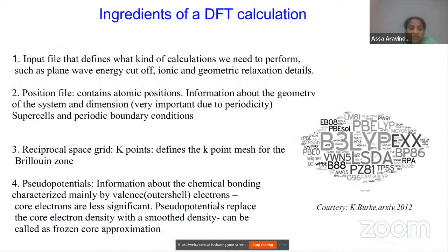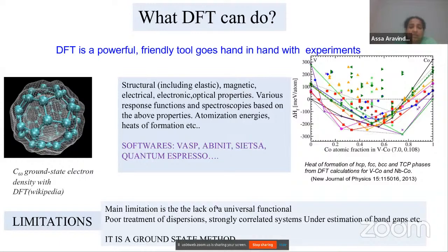But even though we can calculate all these things, the main limitation, as I was telling, is the lack of a universal exchange correlation functional. And for certain systems, when you use DFT, you should be very careful. For example, Van der Waals monolayers, the treatment of dispersions, you should be very careful. And also there is underestimation of band gaps for strongly correlated systems. So you need to know what system you are using and what material is best suited for that. When you compare with experiments, it's good to have a qualitative comparison rather than a quantitative comparison. For example, we calculate the band gap of some insulator as 3 eV in experiment. When you do DFT, maybe you can only get like 2.5, that much accuracy is maybe only possible to achieve in some cases. So you should be aware of that. But nevertheless, we can see the trends, how the trends are varying, how the electrons are interacting, all these things. So it's a ground state method, and we should keep that in mind when doing a DFT calculation.